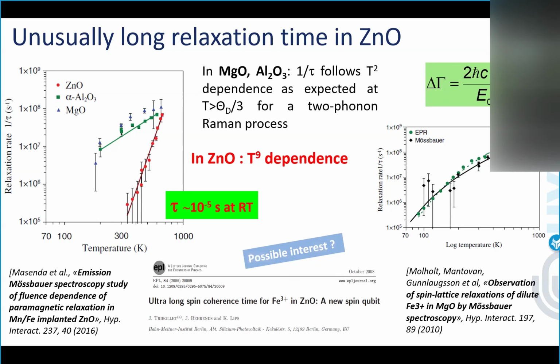But before saying that, at that time we measured a relatively long spin relaxation time of 10 to the minus 5 seconds, contrary to other oxides where we measured much shorter relaxation times. And probably there could still be some interest.